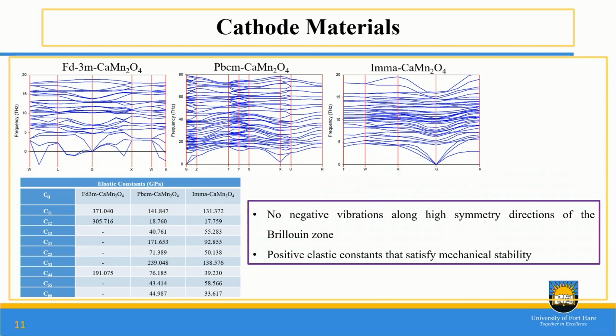So we have also gone on to calculate their stability, to see how the atoms vibrate when the material is in operation. We have seen that the PBCM and the IMMA compounds offer good dynamical stability as well as mechanical stability, which means that in terms of safety, these structures are very much preferable. Then the FD3M does have some negative vibrations along the high symmetry directions, but they are not as severe as one would think. So probably all of them show good promise when it comes to mechanical and dynamical stability.